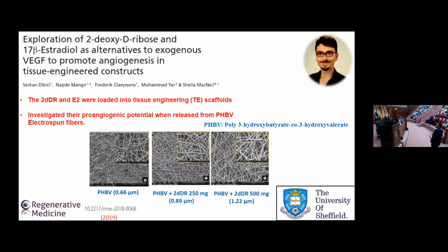At this stage, we also produced electrospun fibers, and variable concentrations of 2-deoxy-D-ribose were loaded. This is the control case, where there was no 2-deoxy-D-ribose, and the fiber size was 0.66 micron. With 250 milligrams, the size increased, and it increased further with 500 milligrams of 2-deoxy-D-ribose. Basically, we were interested in seeing which concentration is good.